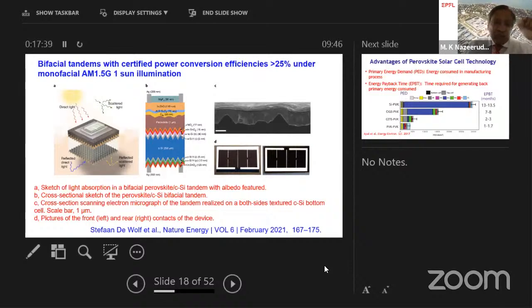On the left panel, the A panel, you can see the possible light absorption phenomena. From the top, you have direct light, and from the bottom, you have an albedo effect, and the reflected light can be absorbed using this material. So that's the importance of this bifacial configuration. This is just a proof of concept. The efficiencies are in the range of 25% that they obtained.